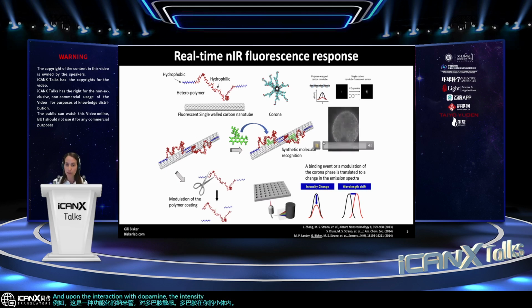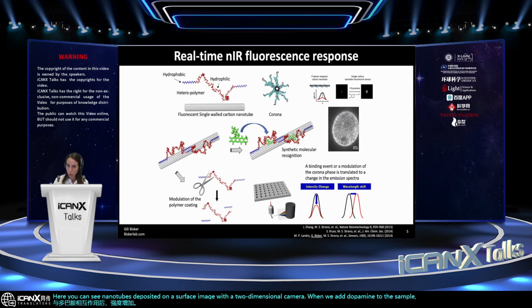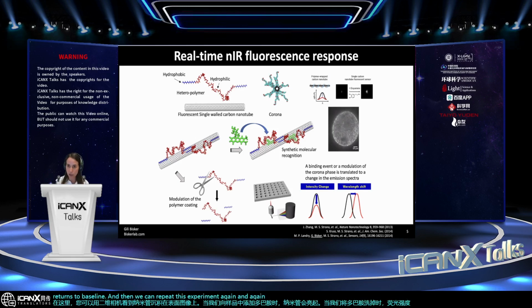Here you can see nanotubes deposited on a surface, imaged with a two-dimensional camera. When we add dopamine to the sample, the nanotubes light up. And as we wash the dopamine away, the fluorescence intensity returns to baseline. And then we can repeat this experiment again and again and again, getting spatial temporal information about dopamine.